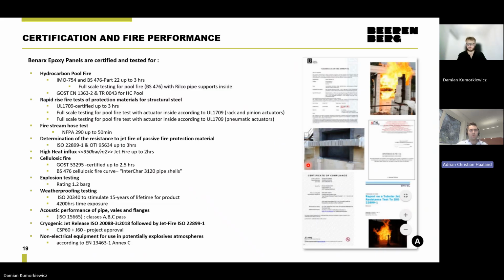For hydrocarbon fire, we typically test according to BS 476 and IMO 754. We've also done some GOST and TR testing historically. Of course, one of the more recognized standards, UL 1709, we have testing and certifications up to above 3 hours. We've also done Firestream hose tests, which we will come back to a little later. And then we have our jet fire testing, both regular according to ISO 22899 and high heat flux, the so-called 350 kilowatt tests. We've also done some sporadic testing within cellulosic fire for building fires. We've done explosion testing. The presentation says 1.2 bar, but we recently did testing up to 8 bar. So we are quite advanced on that front.